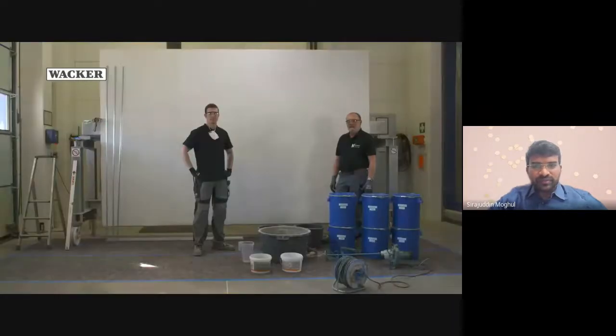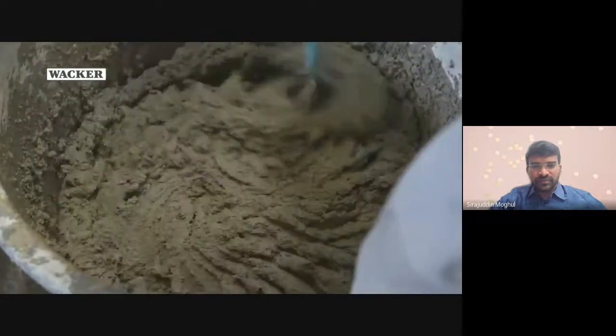The two workers start with the left side using the thin bed technique. Since the mortar bed is only 3 to 5 millimeters thick, they first apply a simple wall troweling compound. This is to level it.